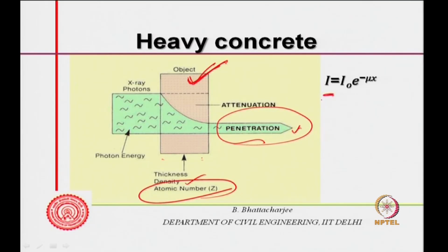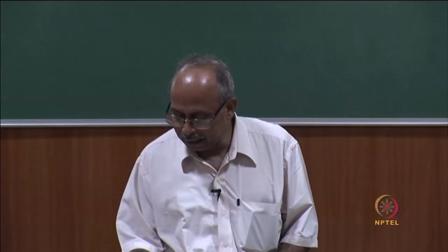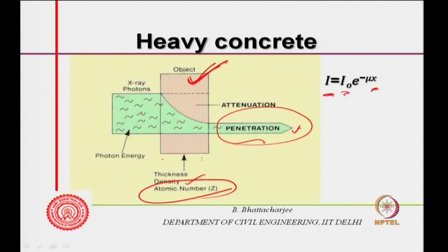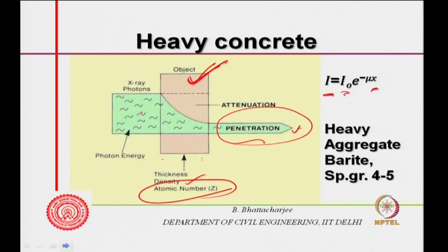The radiation that you get is I = I0 e^(-μx), where I0 is the incident radiation. So, this μ depends upon density, thickness, etc. X is the thickness, and μ depends, amongst other things, upon density. There are a few other factors. Therefore, for heavy aggregate we use barite or hematite, and their specific gravity is 4 to 5. So, this is the concrete.